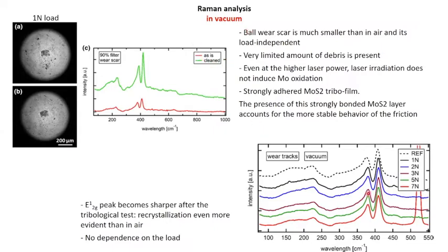And again, we analyzed the order of the film, still analyzing this feature in the Raman spectra at different load. And again, we found that this peak gets narrower, and also in this case we did not find any dependence on the load, but the recrystallization seems to be more effective in the case of measurement in vacuum with respect to the measurement in air condition. And this probably contributes also to the best behavior that has been recorded in absence of humidity.